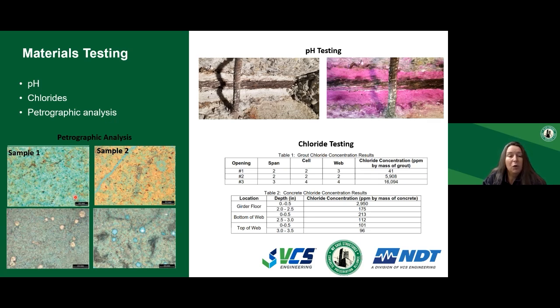The images below show an example of pore infilling for sample 1. So in sample 2, pores are blue, which means they were empty and the epoxy was able to fill them. But for sample 1, the pores were filled with secondary ettringite, which indicates exposure to external moisture.